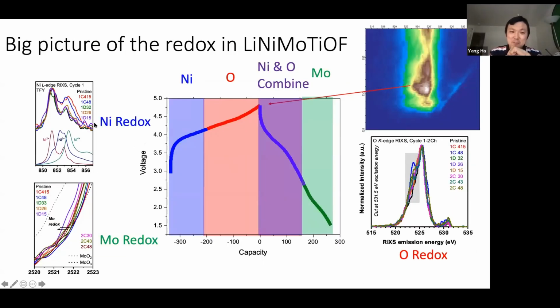So with that, we can combine multiple techniques. In this lithium nickel molybdenum titanium oxide fluoride material, we can combine the nickel L-edge, the molybdenum L-edge, and this oxygen RIXS. And of course, we also measure the titanium emission to show that there's no titanium redox. And we can couple this with the electrochemical profile. When you charge it at a low voltage, it's mainly the nickel redox. And at high voltage, the nickel redox saturates, and then it's the oxygen redox that's kicking in.